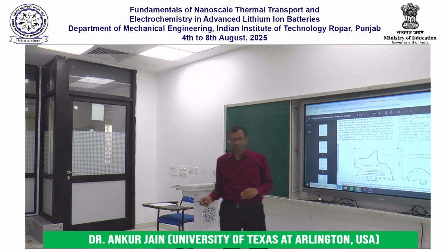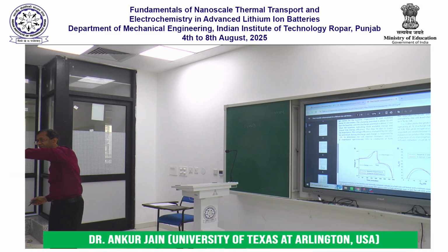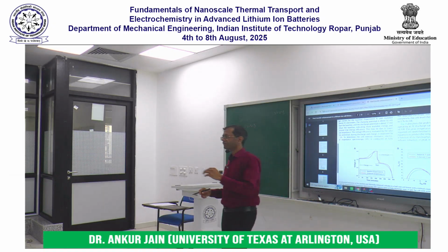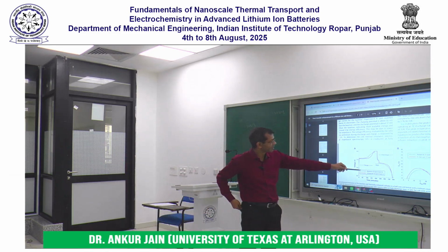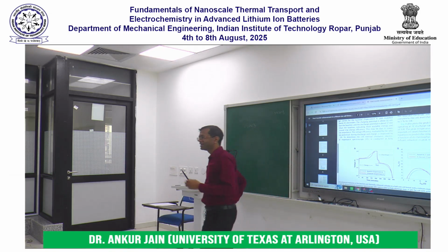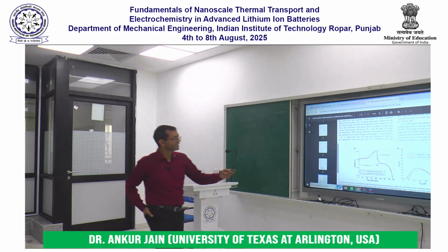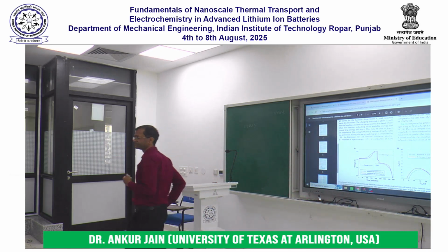So here what we did was that we took these 2 cells that we had built, one with the aminosilane molecule, one without the aminosilane molecule, and then we charged and discharged those cells for a few cycles, for only about 10 cycles if I remember correctly. Okay, and we showed that the baseline experiment and the enhanced experiment had more or less, not identical but more or less the same discharge characteristics. The EIS curves were also not too different from each other.